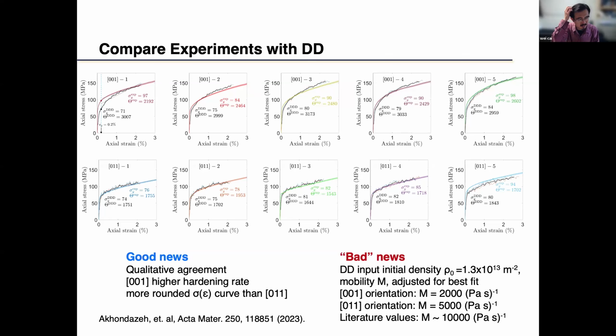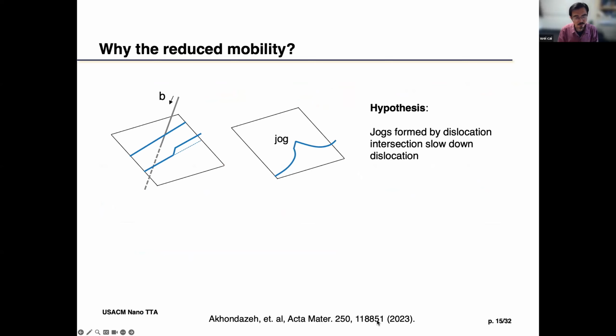So how can the mobility actually depend on which orientation we load the sample? That doesn't make sense, okay? So in this paper, we offered a conjecture. It's something that I always worried about anyway. In crystal plasticity, in plastic deformation, the dislocations are moving around, and the dislocation on one slip plane will cut the dislocations on other slip planes. And by nature of the dislocation, whenever it goes across, it produces a slip, right? So they will basically cut each other and produce little steps on each other. And sometimes those steps are out of the slip plane of the original dislocation. So those are called jogs. And the jogs could slow down the dislocation.